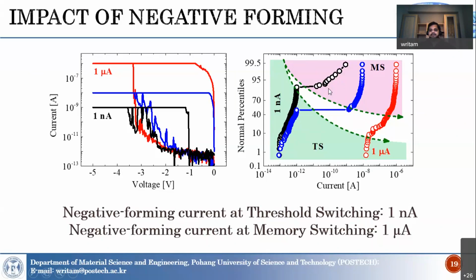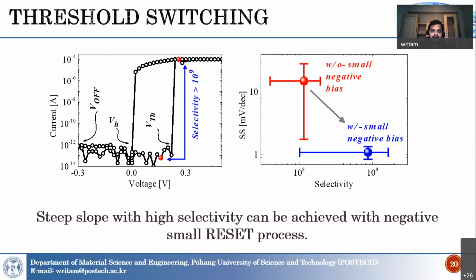So those are the dilemmas of the same device, but with the proper biasing scheme we can change it. With the proper biasing scheme, we can achieve selectivity around 10 to the power 9, with a subthreshold swing around 1 millivolt per decade, which is quite good, and selectivity of at least 10 to the power 9.